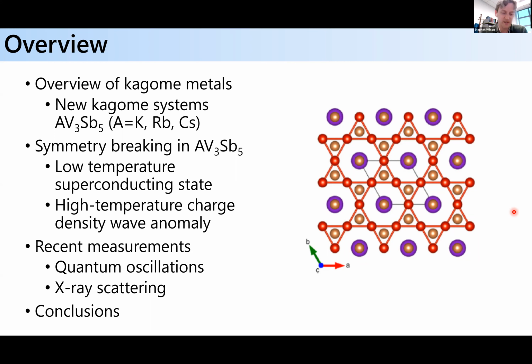In particular, there's two phase transitions. One is a charge density wave phase transition, which is interesting in and of itself. And the second is a low temperature superconducting state, which is potentially unconventional. I think that's not quite established yet, but I'll try and summarize what I think is known right now. But the superconducting state is also interesting because of potentially topological surface states that could interact with it. And then some of the recent measurements I'll be presenting will be some quantum oscillation measurements done by our group, as well as some X-ray scattering.